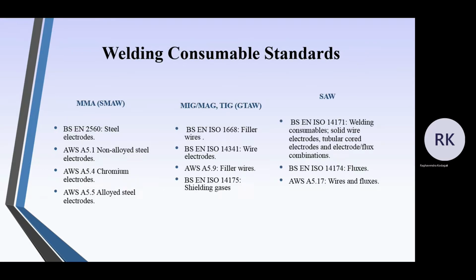Welding consumable standards, well, for manual metal arc SMAW, we have BS EN 2560 steel electrodes and AWS A5.1 non-alloyed steel electrodes, A5.4 chromium electrodes and A5.5 alloyed steel electrodes. Whereas when we go to GTAW, it's controlled by ISO 1668, ISO 14341, AWS A5.9, and ISO 14175. The shielding gases are for that.